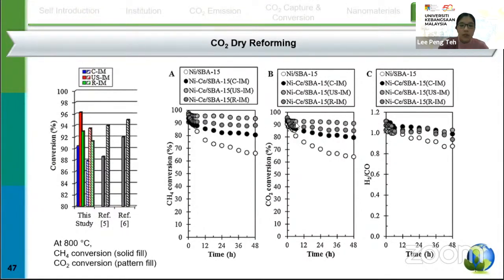For the CO2 and CH4 conversions, because for CO2 dry reforming you will have two reactants, one is CH4, another one is CO2. So CH4 plus CO2 will produce H2 plus CO. In this case, for the ultrasonic impregnation method, we have a very high CH4 conversion, a high CO2 conversion, and we produce an H2 to CO ratio of about 1. And it can be sustained to 48 hours.